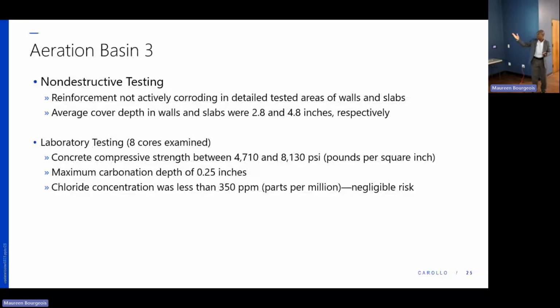Carbonation depth, we have 0.25 inches. When we looked at that, we talked about carbon dioxide attacking the chemicals in the concrete. We have 0.25 inches of carbonation. Our clear cover is 2.8 at these walls, and so that's also not of concern. And then chloride concentration, when we did all our chemical testing in the lab with the amount of chloride ions in it, we are coming to 350 parts per million, which is the benchmark. You want negligible risk. And so the structure is not at risk from chlorides.